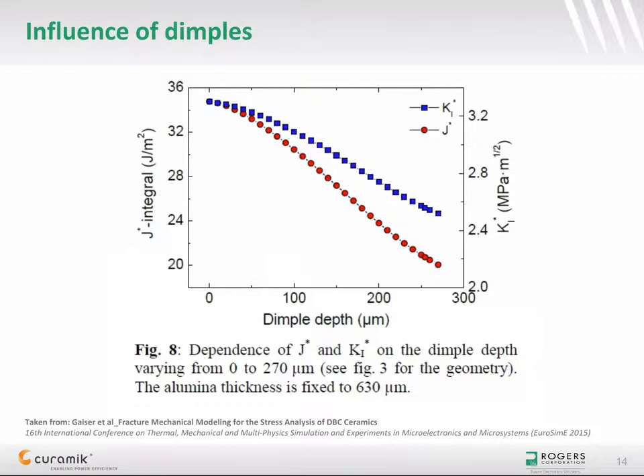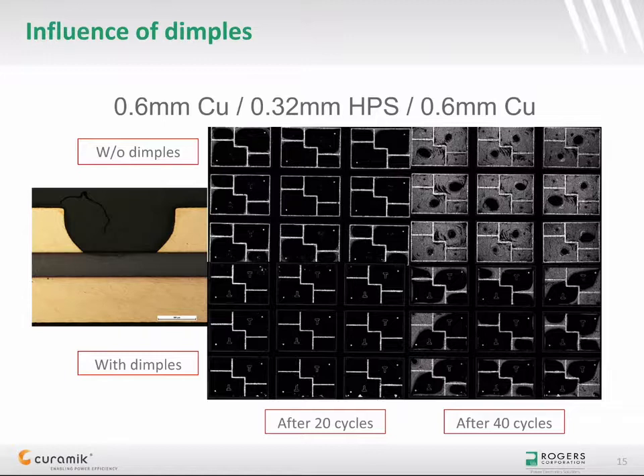But how do dimples act as stress relief? This is the result of the mechanical weakening of copper by removing it partially. This means that there is less copper material applying compressive forces which are critical for the ceramic. Finite element modeling shows that there is an almost linear decrease of the stress in the ceramic for increasing dimple depth. This effect can be observed on the acoustic images for 0.6 mm thick copper bonded on 0.32 mm zirconia toughened alumina with and without dimples. In both cases, substrates do not show any degradation after 20 cycles. After 40 cycles, substrates without dimples are completely delaminated, while substrates with dimples look much better even though degradation has already started.